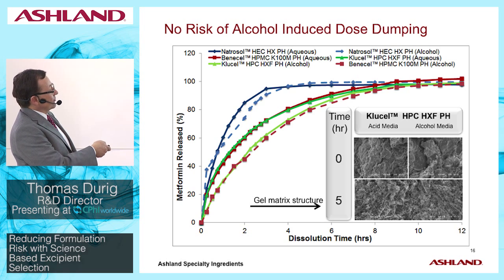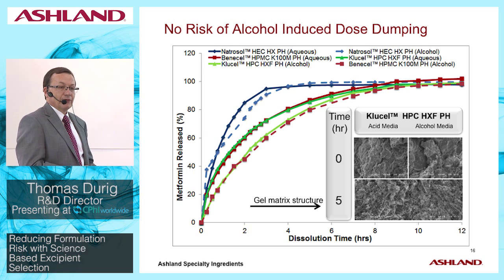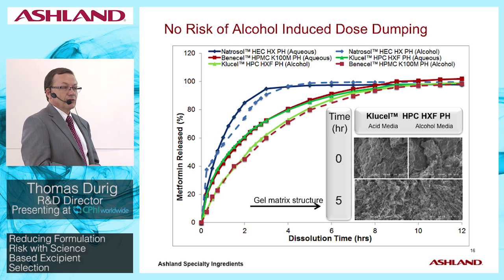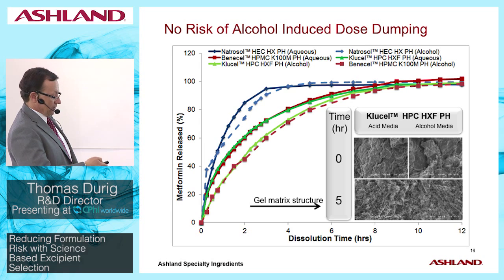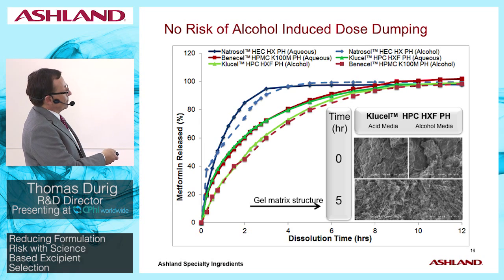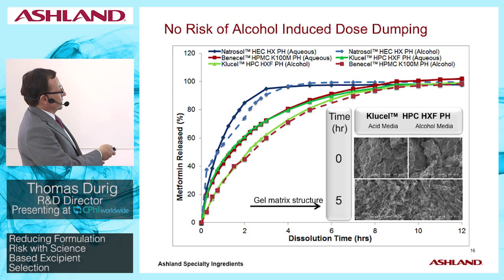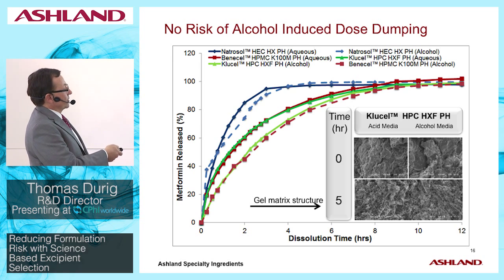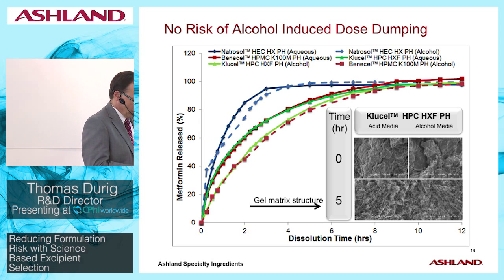In fact, there's a slight retardation in the release profile as we add more alcohol due to the increased gel strength. And as you can see here, if you look at the matrix structure of the tablets after dissolution, it's quite clear, at 5 hours dissolution, that the matrix structure looks very similar, whether it's simulated gastric fluid or simulated gastric fluid with 40% alcohol.